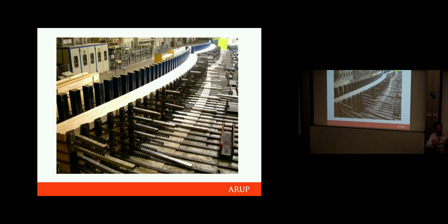Now, what I've shown you there is a curved glulam beam, because while the glue is still wet, it's really, really easy to pull those thin planks into a curved shape. Now, you can imagine if you try and bend them too much, they will simply snap. Roughly the limit, the minimum radius, is something like 200 times the thickness that you can bend them to. So if you think that we normally have planks which are maybe 3 or 4 centimeters thick, the minimum radius is about 6 meters.